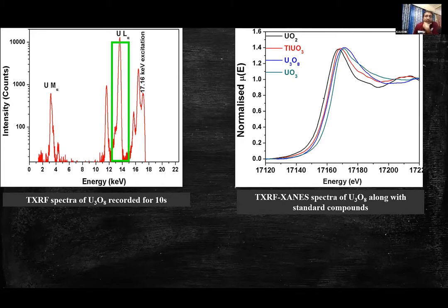You can see that as you go from plus 4 to plus 6, from uranium oxide to UO3, the edge position changes from lower energy to higher energy. This is because as the oxidation state of uranium increases, it requires more energy to knock out the inner electrons from the uranium atom. If you see the edge position of uranium in U3O8, it is situated in between plus 5 and plus 6.